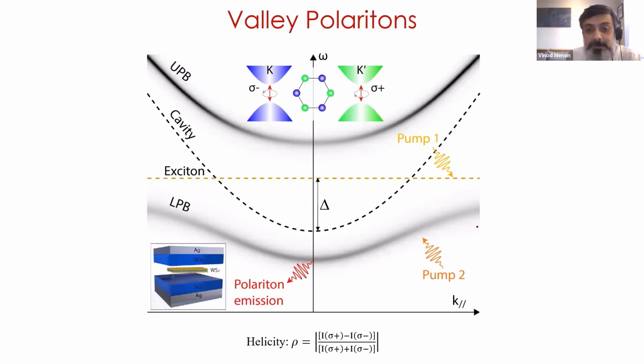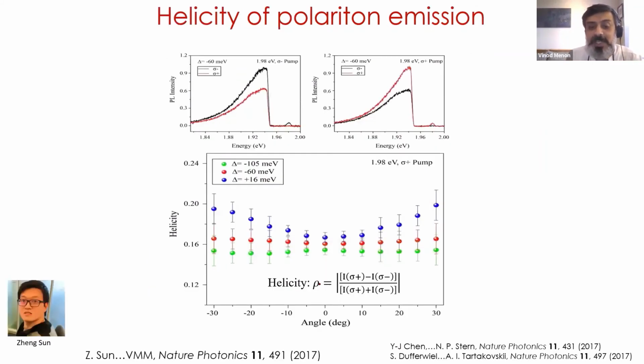What we were able to show was that these polaritons, or these strongly coupled states that form in these systems, also preserve the property of this valley polarization. So we just make a strongly coupled cavity, we study the polariton emission here, we come with sigma plus light, we ask the question, what is the helicity of the light that is coming out here? Is it sigma plus or sigma minus? And we were able to show that indeed they follow the same helicity principle, or the valley polarization property. And in fact, what is interesting with the polaritons is, as you make the polaritons more photon-like, you can see the helicity actually increases as you go towards more exciton-like at large angles, and then it decreases at zero angle, because there it is very photon-like. And so this was work reported in 2017.